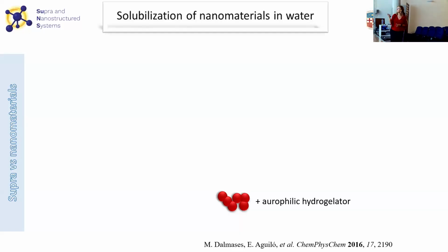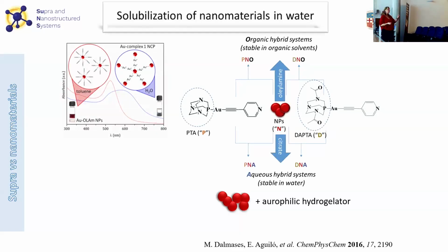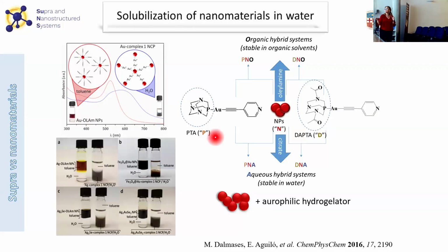The second example of our work on materials was how we can affect these metallophilic interactions with nanomaterials. So what we did was make react a solution having our hydrogelators based on gold(I) assemblies with nanoparticles. And what we observed is that the color of the solution with the nanoparticles disappeared immediately when it was in contact with our hydrogelators. This was because the hydrogelators were making some gold-gold interaction with the nanomaterials and transferring the nanoparticles to the aqueous phase. So this was an easy way to solubilize nanoparticles in water.